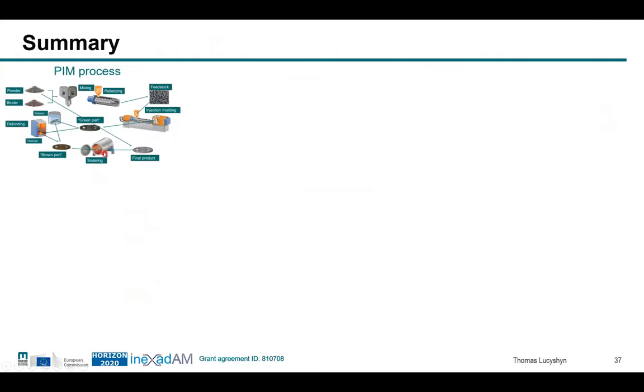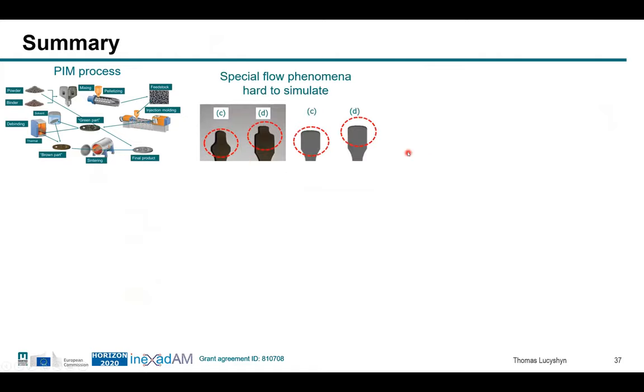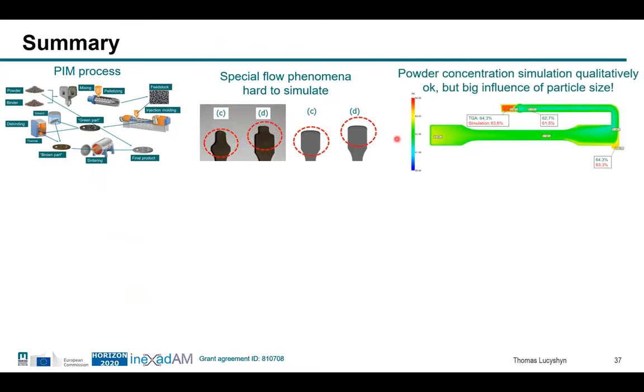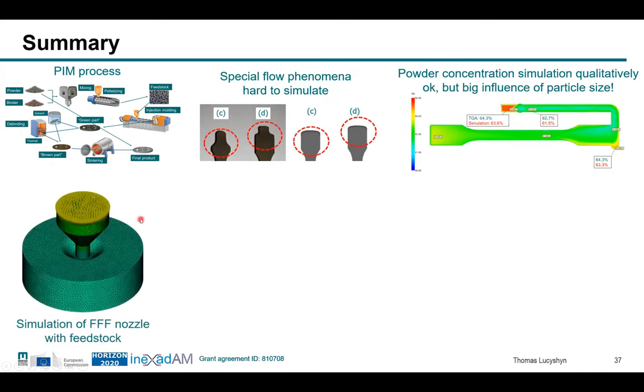Okay, then summarizing my talk, I introduced you to the PIM process. So alternatively to additive manufacturing, you can also use injection molding to produce ceramic or metal parts, using injection molding as an important intermediate shaping process. I showed you that we have some very special flow phenomena with these materials in injection molding, which are still hard to simulate or not yet possible to simulate correctly. I also showed you powder concentration simulation, which is already possible. The qualitative results are already useful. You see differences, you see where problematic zones are, but still the absolute values are not where we want to have them. And I also showed you an approach to use the injection molding software also to simulate some aspects of this FFF process.